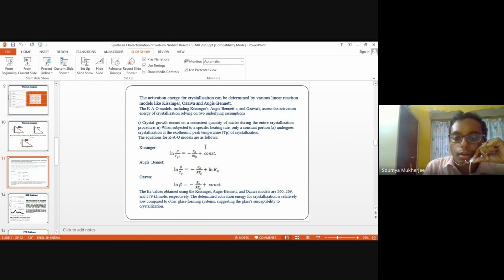And these values are found to be quite low compared to other glass ceramic systems, which shows that sodium niobate systems are quite good for having this crystallization within the glassy matrix. And within the same system, if we compare, the Kissinger method is giving a much lower value, that is the Kissinger mode of linear variation of crystallization.